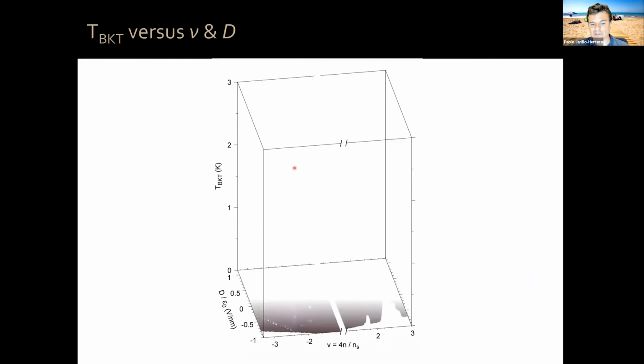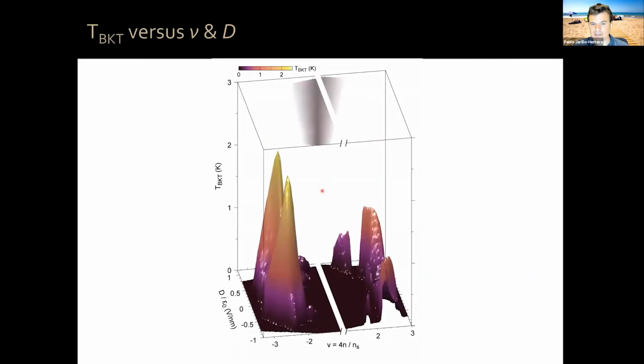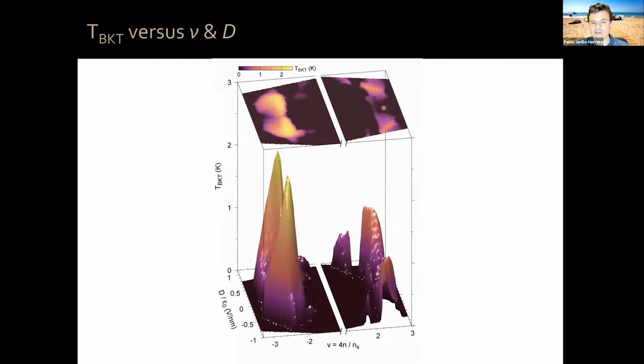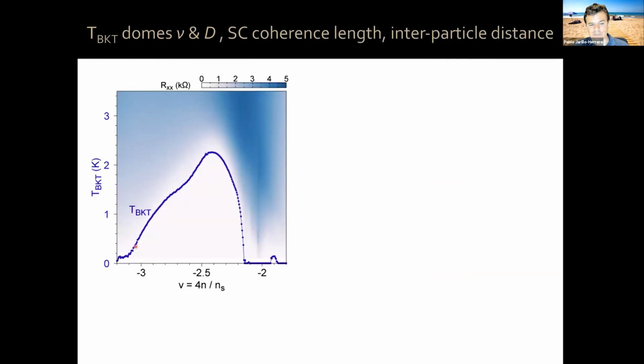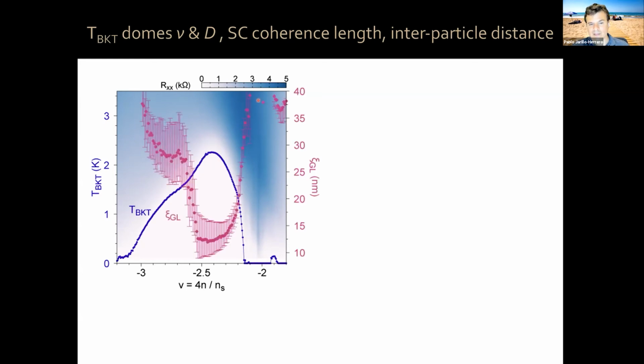We can measure the critical temperature as a function of filling factor and displacement field. I can project it onto this axis. And then I'm going to show you cuts along displacement field and filling factor directions, okay? So this is critical temperature versus filling factor at optimal displacement field. You can see two superconducting domes for electrons and holes around 2 holes per moiré unit cell. I can measure simultaneously, in the same device versus the same filling factor, the superconducting coherence length, the Ginzburg-Landau superconducting coherence length, and it gives me this, okay?